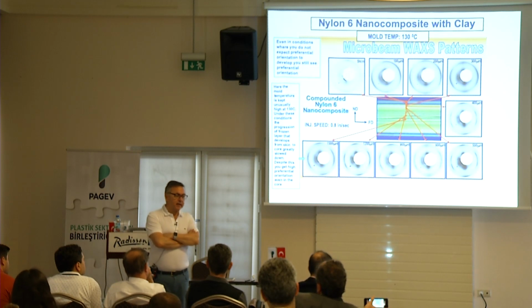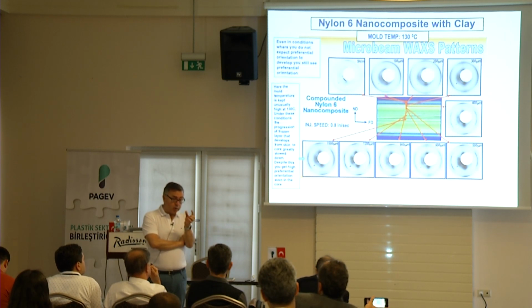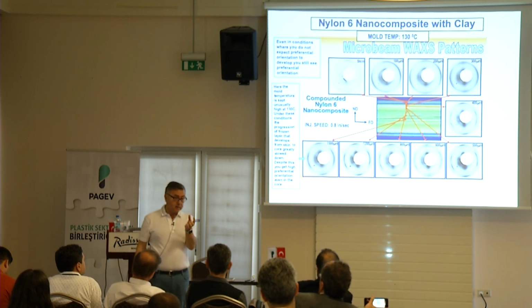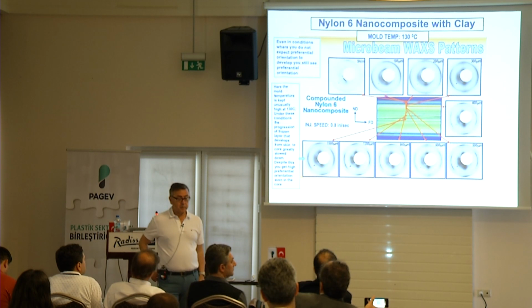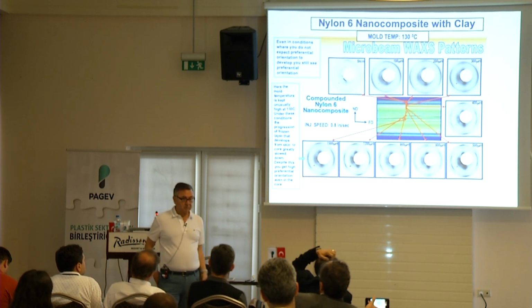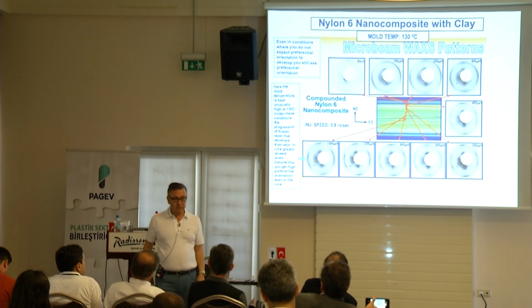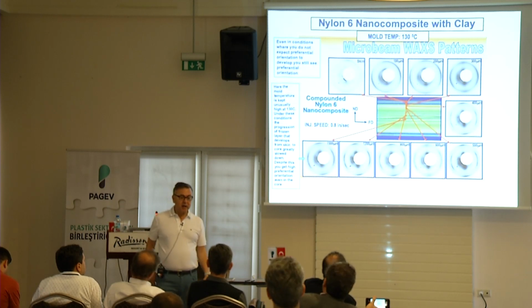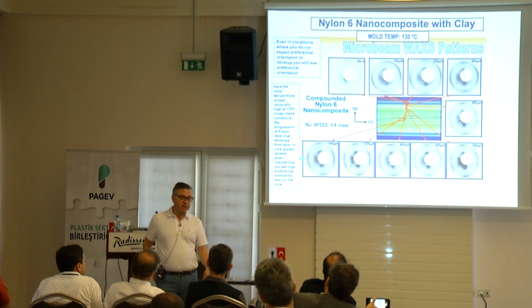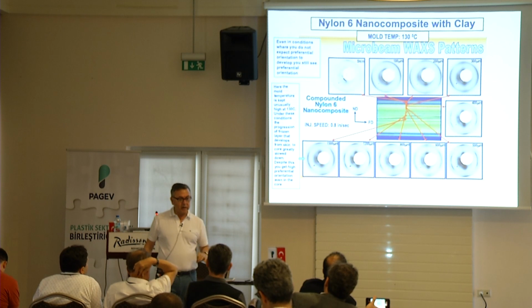I think the clays are 1 or 2 microns in plane. If your film thickness is 1 or 2 microns, they are about the same dimensions, so you will create defects. Inevitable. But in injection molded parts, which are thick, that doesn't happen. The only other option is to start with clays that are very small in plane dimensions. They do have synthetic clays. If you use synthetic clays with smaller in-plane dimensions, you might have a better chance of getting fewer defects in the material.